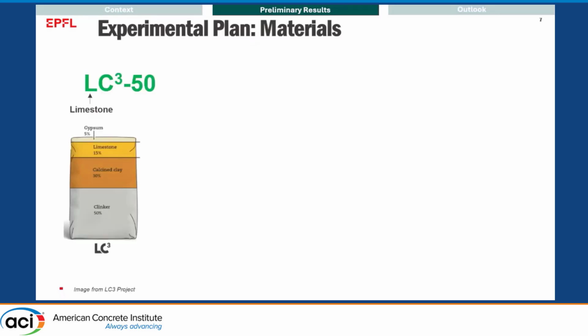Of course, I've been using LC3, limestone calcined clay cement. For those of you who don't know, LC3 cement was first formulated and developed at a lab at EPFL. And here is a picture of a cement bag with LC350. 50 refers to the amount of clinker replacement. So 50% of clinker is replaced with calcined clays and limestone. Here it is a 2:1 replacement. As you can see, it is 30% to 15% of limestone. So it is a 2:1 replacement.